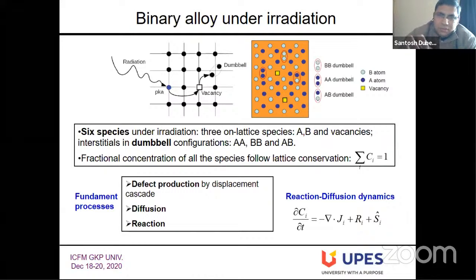So defect production will put defects inside the material, which will lead to atomic transport inside the material. The concentration of any species, whether A, B, vacancy, or the interstitial species, should depend on the diffusion process, the reaction, and the production of defects. So this is a reaction-diffusion type equation that we have to construct. Now this is just the skeleton of the equation. We need to derive how the flux of each species will look, when these defects will react with vacancies, like recombination reactions, or we can have a change in the dumbbell type, like pure interstitials converting to mixed interstitials and so on.